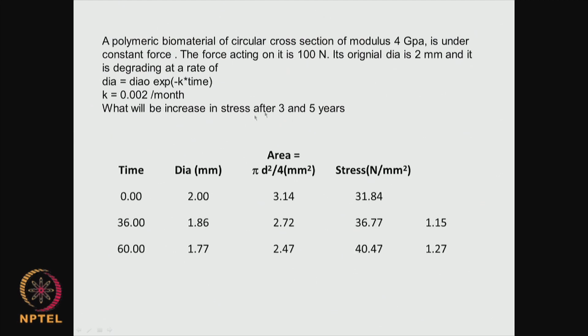3 years is 36 months, 5 years is 60 months. So, original diameter is 2 mm. So, diameter changes as a function of e power minus 0.002 into 36. The diameter has become 1.86 mm, whereas if you take 5 years, that is 60 months, the diameter has become 1.77 mm. So, area is pi d square by 4. Original area is 3.14 mm square. After 3 years, it has become 2.72 mm square. After 60 months, it has become 2.47 mm square.